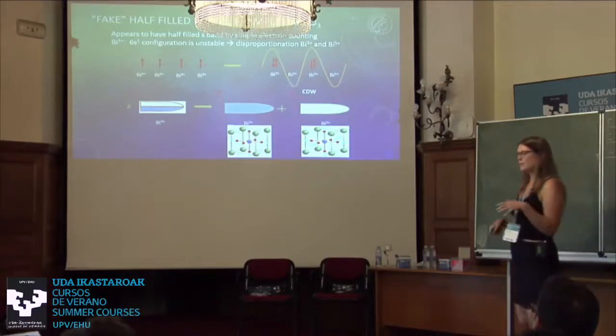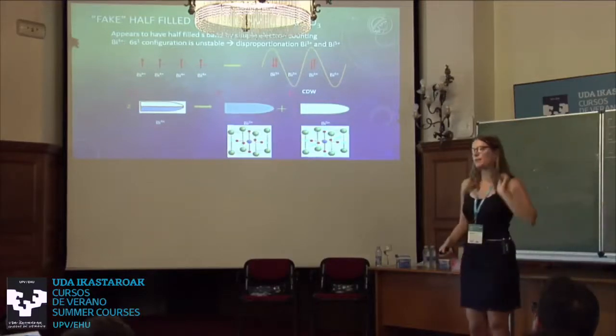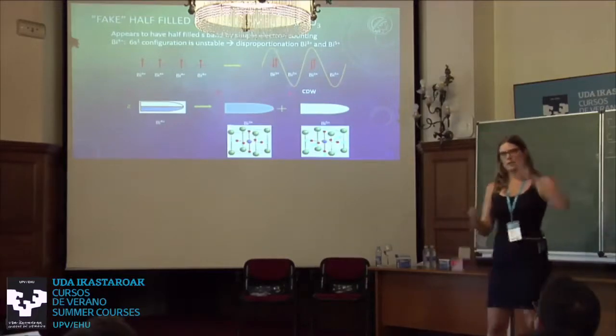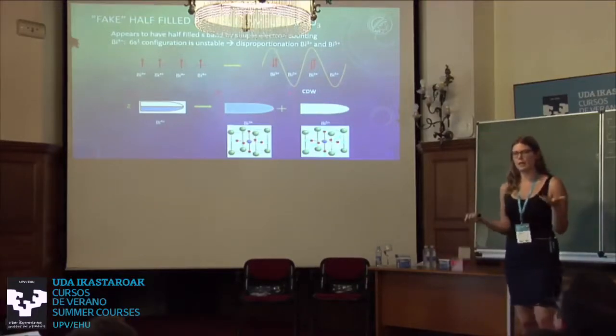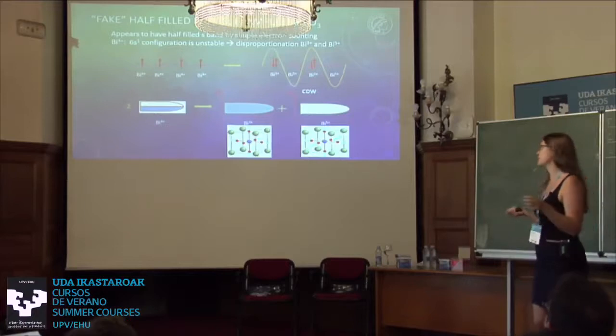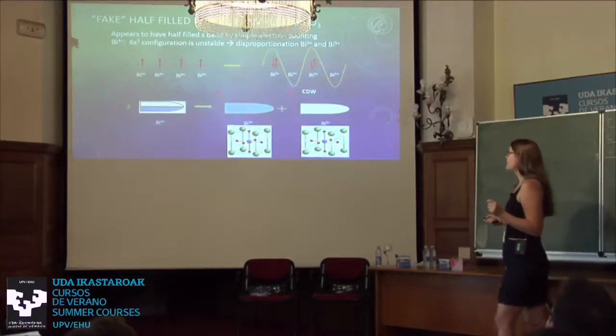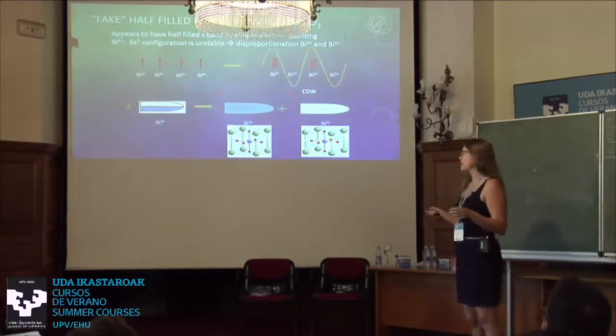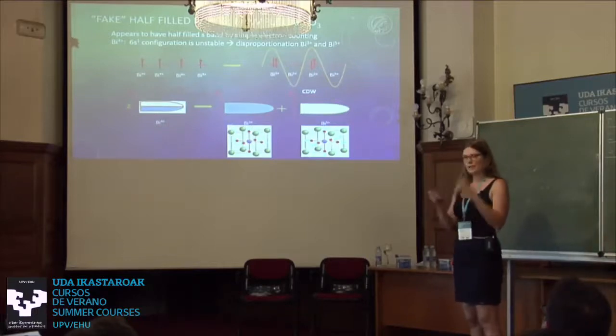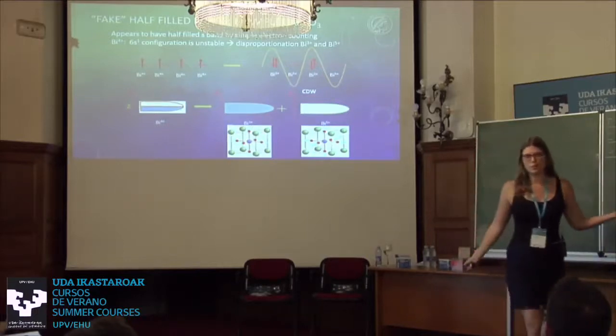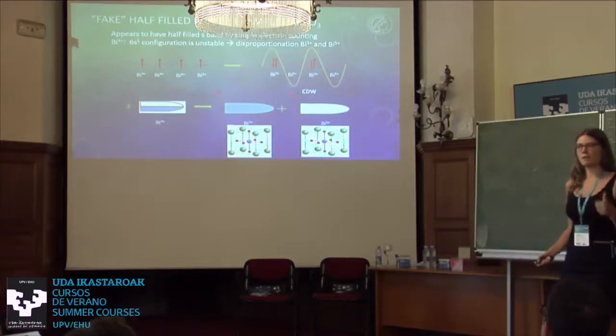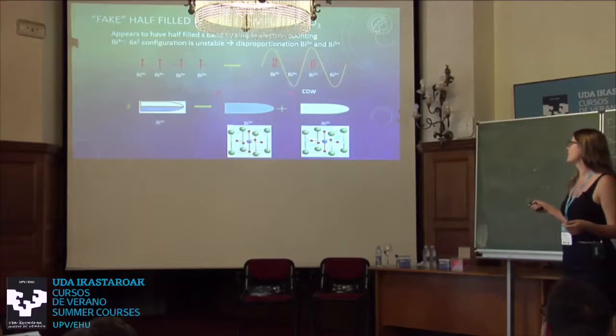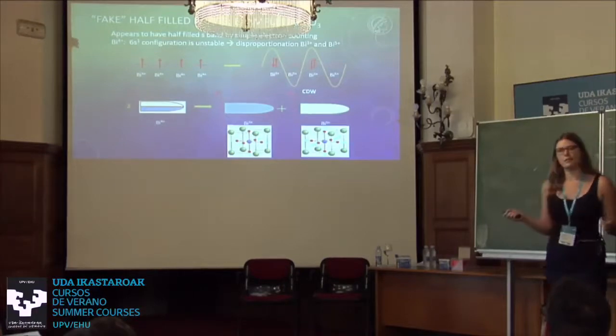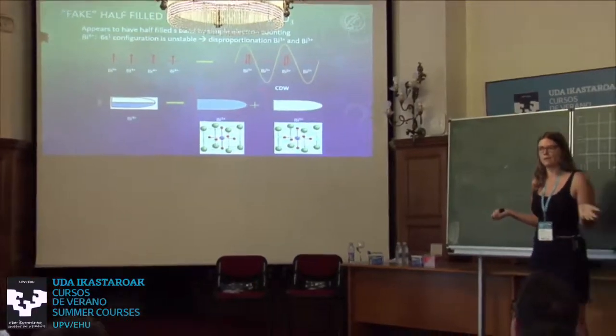And there's lots of literature out there about DFT calculations in an averaged, undistorted structure, and it has a half-filled band and looks very unstable. But if you look carefully at the structure, you see that there are actually small and large alternating bismuth oxygen octahedra. So this means we have 3+ and 5+ bismuth alternating. And so instead of having this filling, we get this filling in a charge density wave, and we again have a band gap and a trivial insulator.